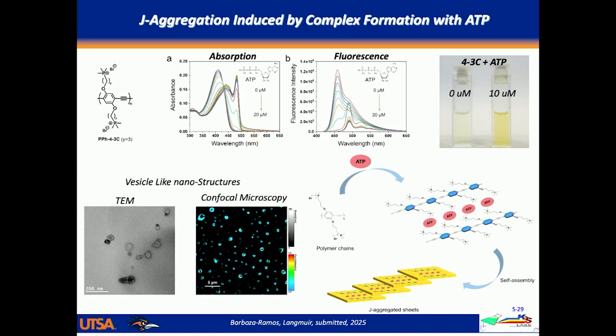For those of you, again, who might be familiar with photophysics, it looks very much like the signature of what's called a J aggregate. And a J aggregate is where chromophores align in a long axis form. So if you think of the polymer chains, somehow they're aligning in such a way that the chromophores are lined up and you get the transition dipoles so that they couple, and it gives this what's called superradiance effect where you get a very sharp and narrow absorption feature, and you also see a sharp emission feature that corresponds to that. This cartoon represents what we think that structure might look like. It's some sort of aggregate that has alignment of polyelectrolyte chains such that the dipoles that are oriented along the long axis can couple, and it's that coupling of the transition dipoles that gives rise to these very sharp absorption peaks.